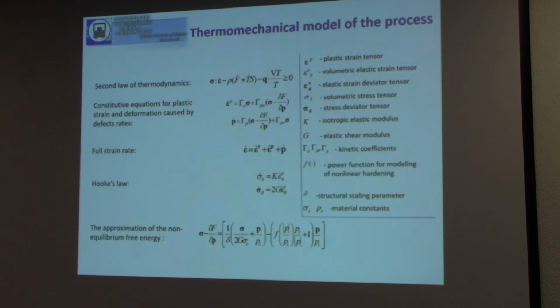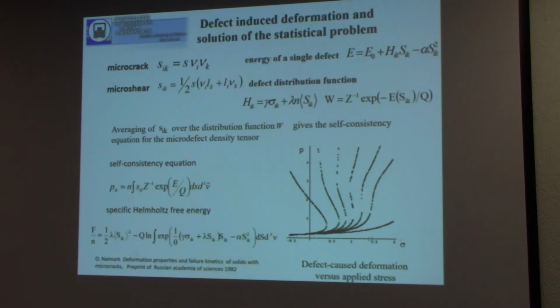It's a dissipation inequality. It was described in another presentation by people from my institute. If we use the local equilibrium condition, we can write a simple equation for the plastic deformation and the structural scaling parameter. And according to our tradition, we use the structural scaling parameter as an additional structural sensitive variable. And I'm going to show why we use such a kinematic relation for the description. After that we can write Hooke's law, and we are looking for a good approximation of the thermodynamic potential. Why do we use structural sensitive variables as a deformation?